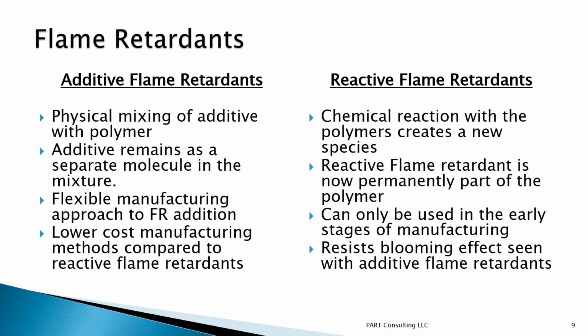The reactive flame retardants are resistant to blooming effects that you can see with additive flame retardants. That is, in an uncured state, when it blooms during the curing process, these materials can come out or separate out of the polymer mixture, and they can form a layer on the surface. Blooming is not a desirable effect, and you don't see it too much today, but it was at one time a particularly difficult problem.